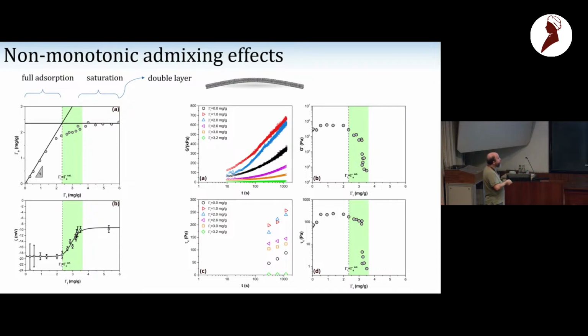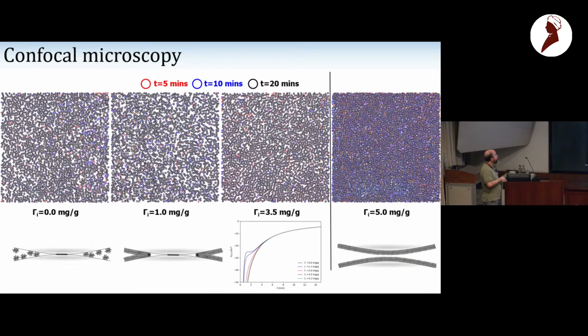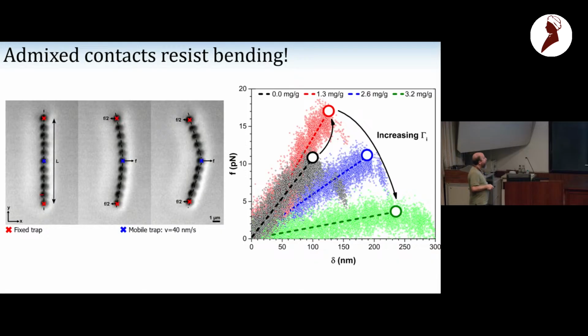And whenever you form contacts, essentially here you still have a modulus, and you have a region where you start to lose the formation of contact. If you're in the region where you form contact, you continue to see aging, but now it apparently depends on the dosage, on the presence of the polymer. If you look at confocal microscopy, this is the bare particles, and you add some small amount of polymer, and you continue to form contact. Eventually here you see that now you have structural dynamics, because now you prevent the contact formation.